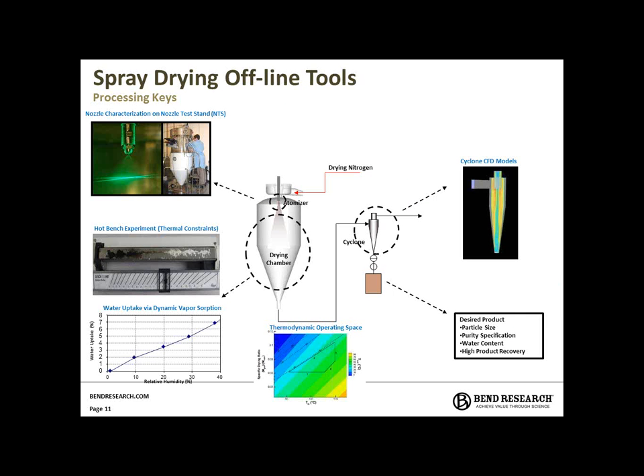Slide 11 shows some of the offline tools we've developed to define the inputs into the spray drying process. We'll run through a couple of these. The upper left-hand corner is the nozzle test stand, which uses a phase Doppler particle analyzer where we can put different atomizer geometries and conditions offline, outside the spray dryer, characterize the droplet sizes, and match droplet size distributions across spray dryer scales, or for other optimization of particle size, not scale related.